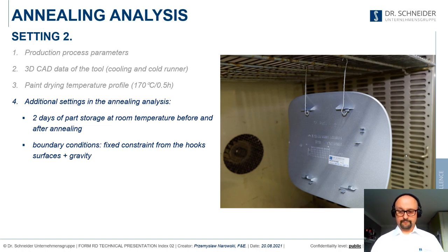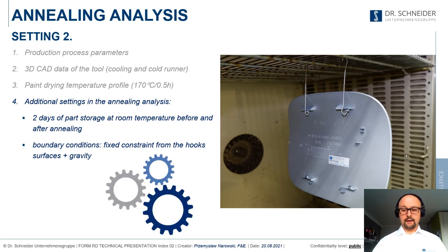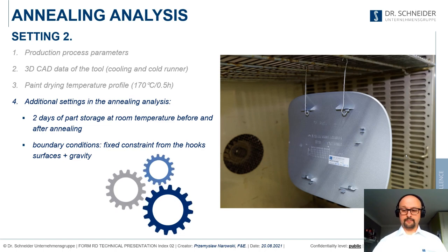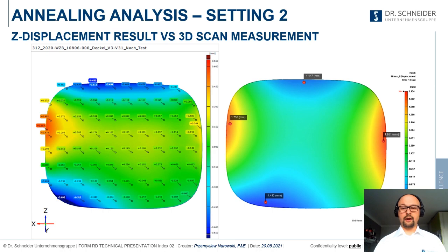We also introduce fixed constraints from these hooks, you can see on the picture on the right, because the part is dried in that position, so it hangs on these two hangers, and it's 3.5 millimeters thick, so it's also quite heavy. So we introduce also a gravity force to make our annealing simulation more accurate. After running the simulation, we observe the new results, and we got a slight improvement, but only a slight one.